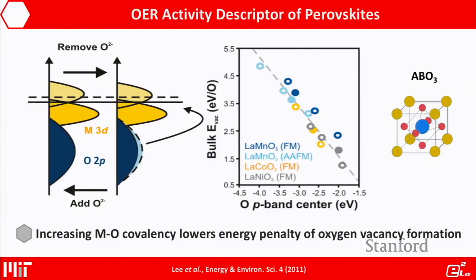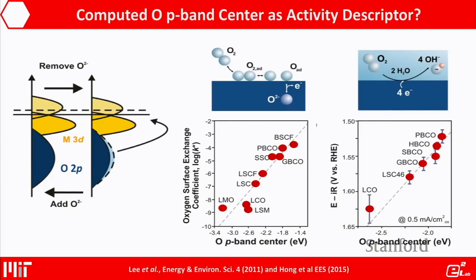So the electronic structure is very important. If you look at the Fermi level relative to the oxygen p-band center, it dictates the energy penalty to create oxygen vacancies. As you push the Fermi level into the oxygen p-band, there's very little penalty to create oxygen vacancies. So the question is, if we push the Fermi level down, essentially we're increasing the covalency between metal and oxygen, and how would that influence the catalytic activity?